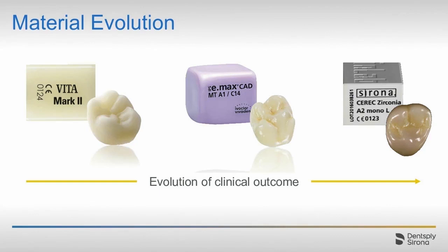Now we move forward to 2016, 10 years later, and we're in the middle of the boom of zirconia, and now zirconia has moved into these chairside systems, which allows us to actually mill and sinter zirconia chairside. This is what's called CEREC Zirconia, made by Dentsply Sirona, and this is a super high-strength zirconia that we can mill in roughly 10 to 12 minutes and sinter in under 15 minutes, which has brought the zirconia process chairside. This is a high-strength, rather opaque zirconia, but it gives us a material for second molars on patients that, for instance, may not want to use gold.